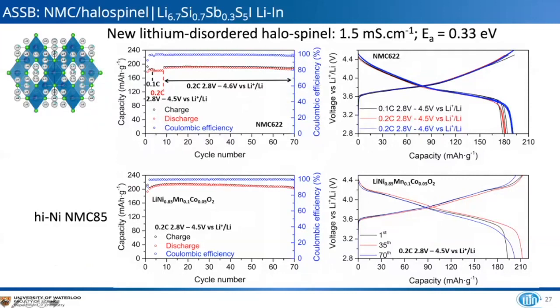And we've since translated this to a new lithium disordered halo spinel, which is, I think, the first in its class. The structure is shown here on the left. Again, conductivities are on the order of 1.5 millisiemens, with activation energy similar, about 0.3. And this shows the data for NMC 622 and for a high nickel NMC material, NMC 85 concentration of nickel. And in this case, we can actually cycle all the way up to 4.6 volts with reasonable stability over 70 cycles. In the case of the high nickel material, we're able to obtain capacities upwards of about 200 milliamp hours per gram, again over roughly 70 cycles. And this is in the window up to 4.5 volts. So even though these electrolytes have a thermodynamic stability window that seems to be about 4.3, clearly there's some kinetic stabilization that enables us to go up to 4.5 or 4.6 volts.